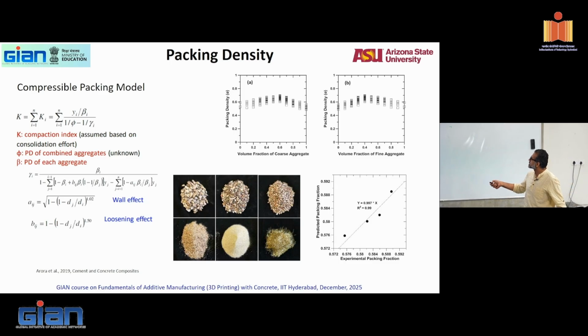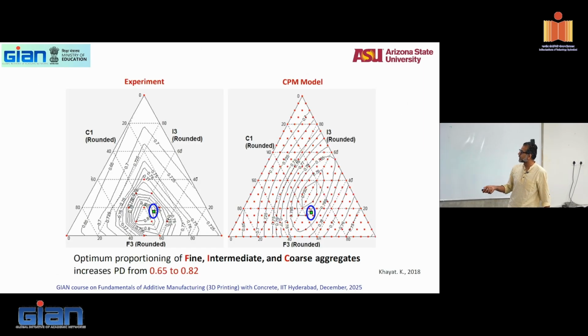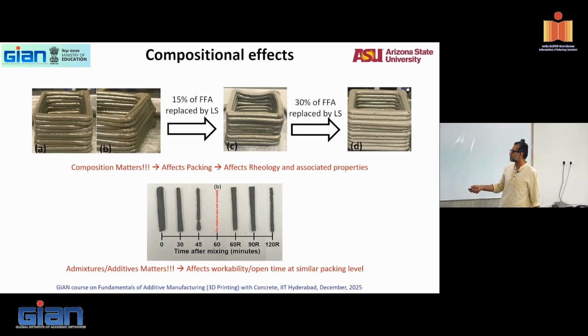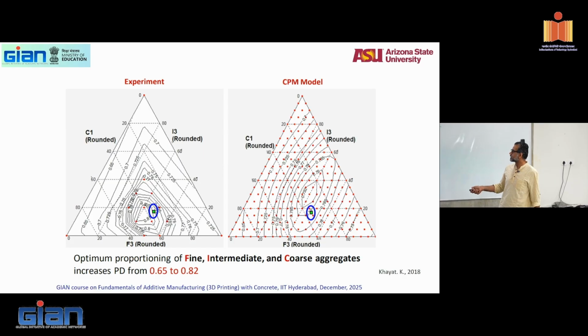Similarly, for a different size distribution, my maximum volume fraction slightly changes. And then my experimental versus predicted shows that my model is good. So this is your packing density calculation using what's called the compressible packing model, exactly based on the theory of how particles pack. And if I do some examples based on 3 different sizes, fine, intermediate, and coarse aggregates, increasing packing density from 0.65 to 0.82, what does this point to? So among these, which one do you think will have 0.82? Fine, intermediate, or coarse? Which one will have it?